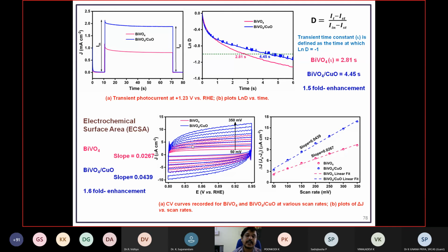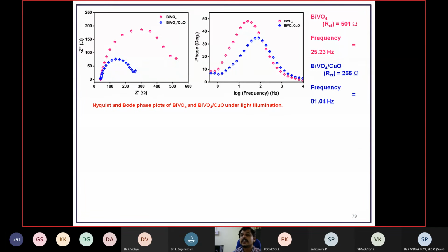Then we have calculated the electrochemical active surface area by varying the scan rate. We plotted the scan rate versus the difference in the photocurrent. The electrochemical active surface area also increased after making the heterojunction, almost 1.6 fold compared with bare bismuth vanadate. Then the charge transfer dynamics we have also studied. Here you can see that the Rct value is very low after making the heterojunction, while the bismuth vanadate showed a very high charge transfer resistance. The frequency for this material also showed a higher value compared with the bare material.